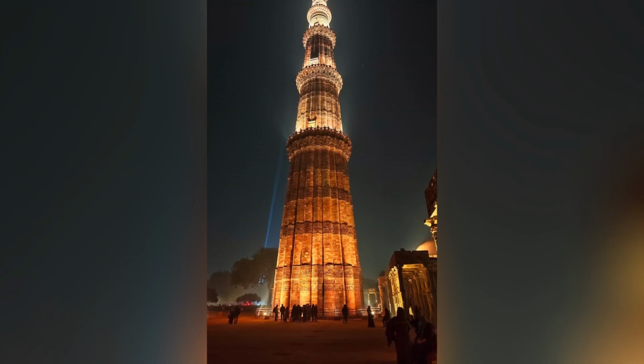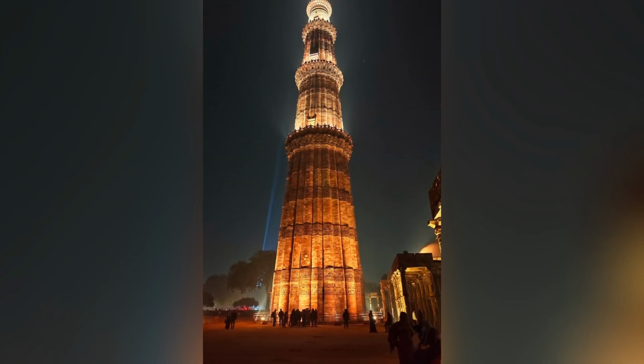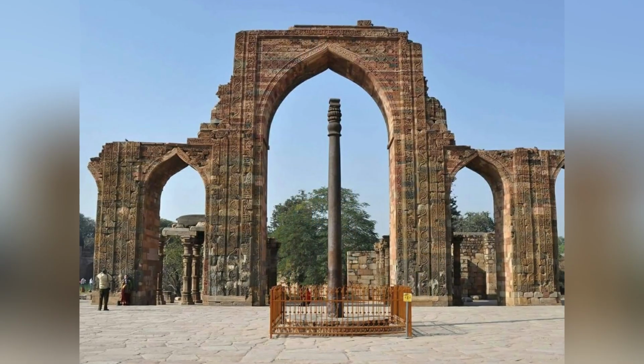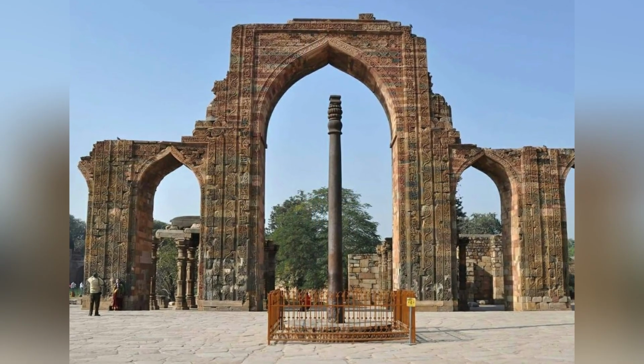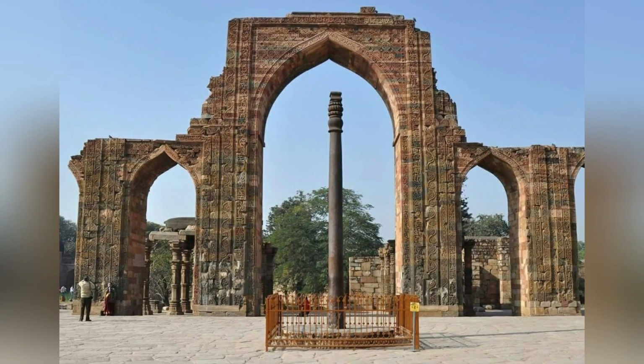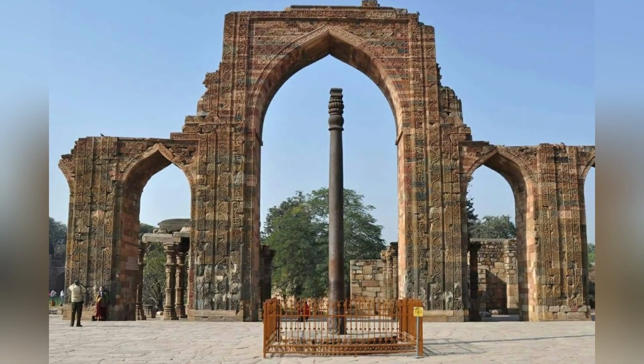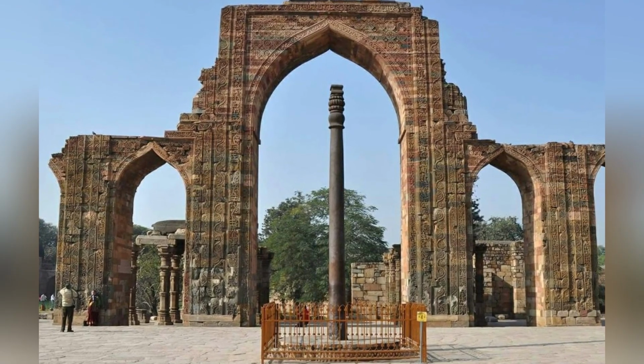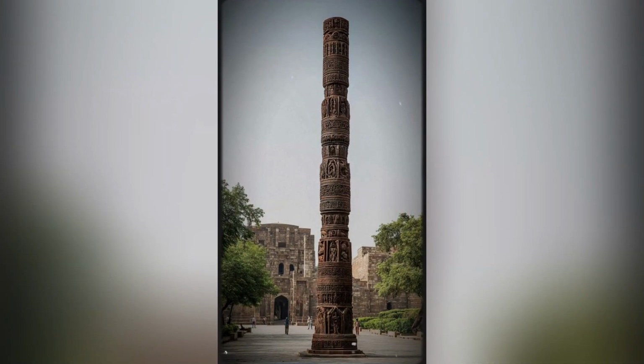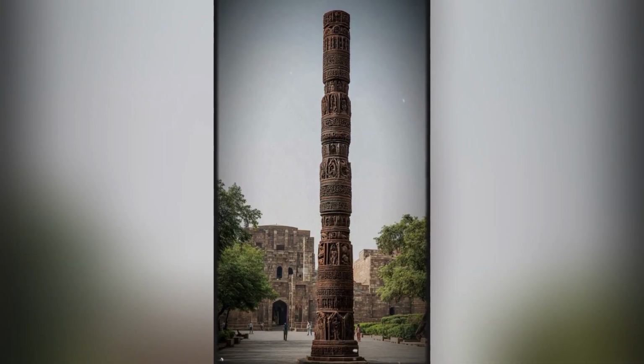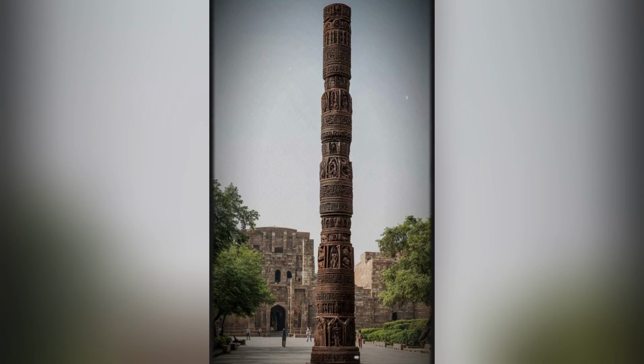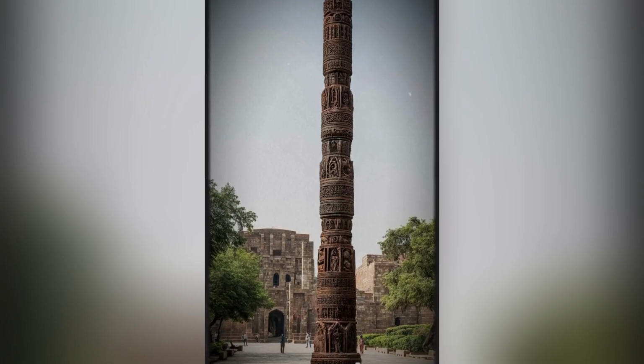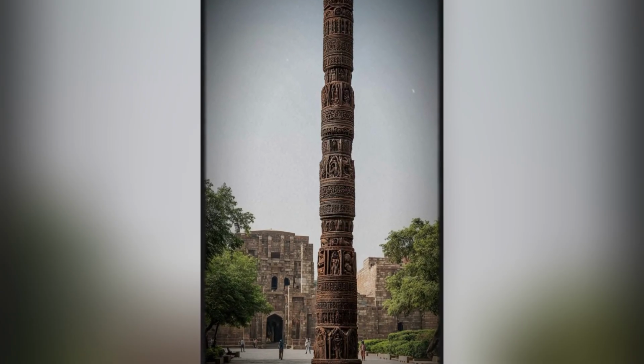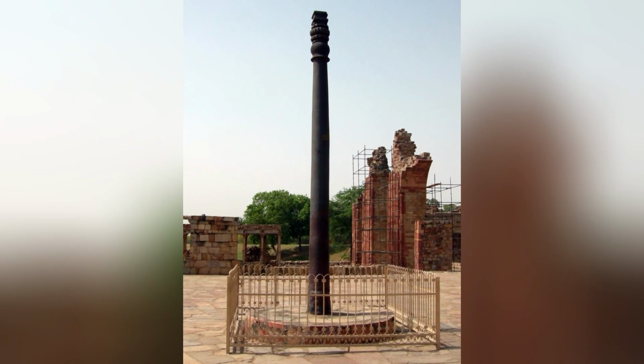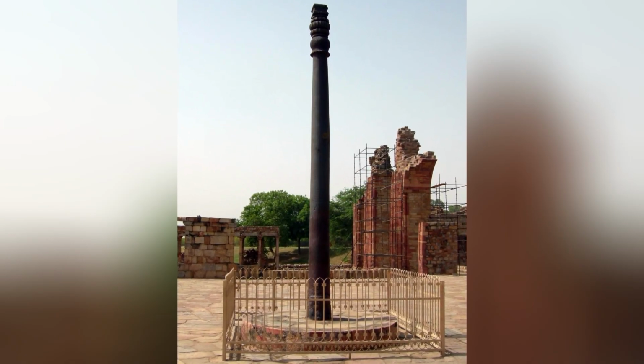The pillar has demonstrated that the specific chemical composition of a metal, particularly the presence of specific minor alloying elements such as phosphorus, can have a dramatic effect on the metal's long-term corrosion behavior, an insight that has led to the re-evaluation of the role of minor alloying elements in the atmospheric corrosion of iron and steel, and to the development of new alloys and surface treatments that are based on the principles demonstrated by the pillar.